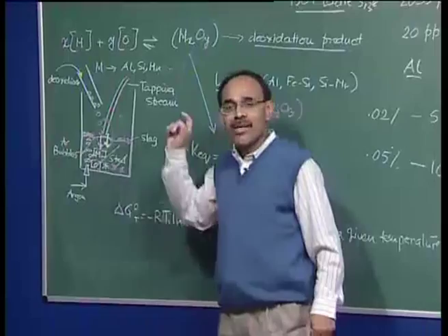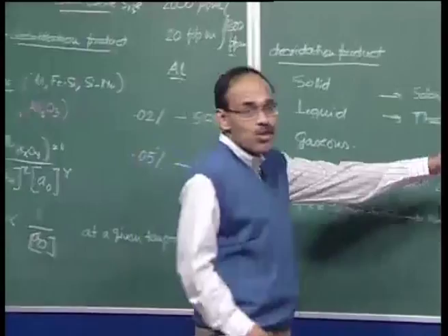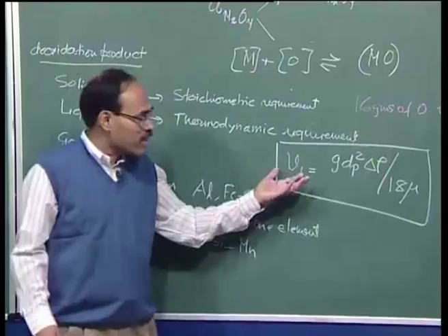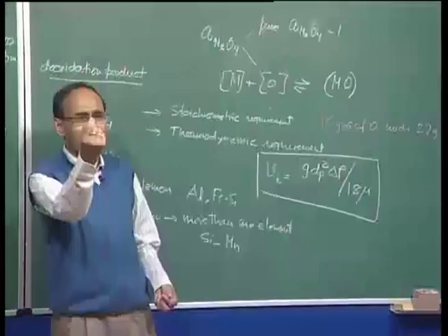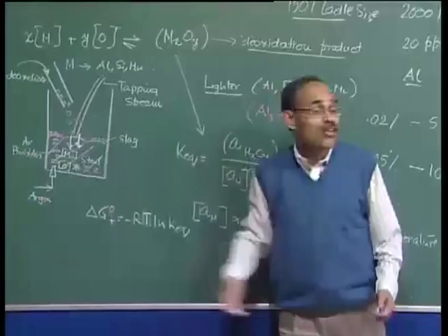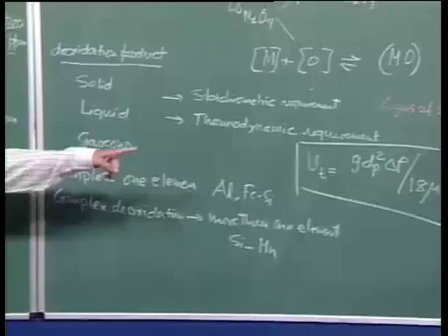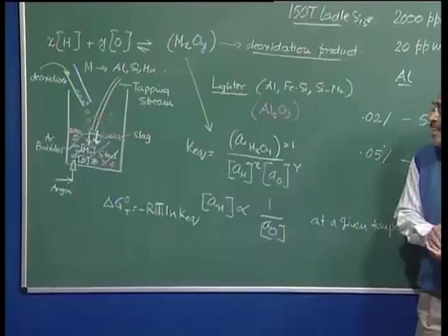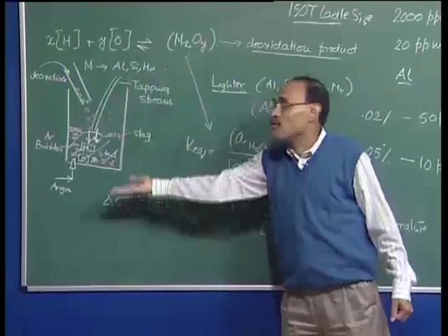So, coming back to Stokes law of settling, given the size range and if I know the bath height, I should be able to find out the possibility of inclusion flotation. We can calculate and show that if the inclusions are of the order of 40-50 microns in size, they virtually have no possibility to rise up and float to the free surface. On the other hand, if the inclusion size is 200 or 500 microns, their rise velocity is so large that in 1 to 2 minutes they should be able to cover the entire depth of liquid and come up to the slag-metal interface,